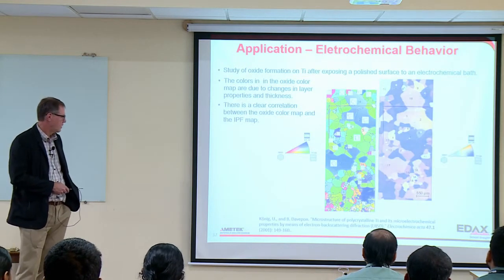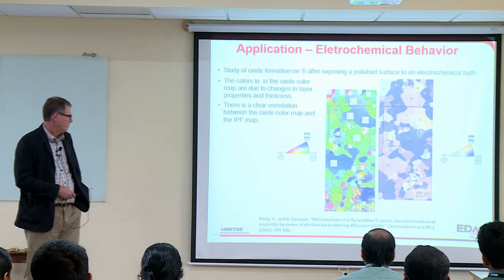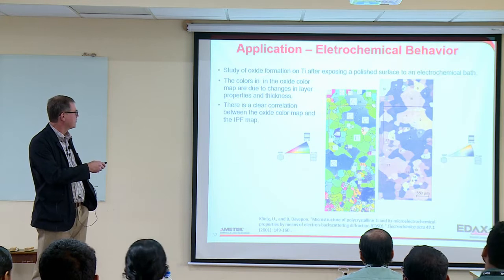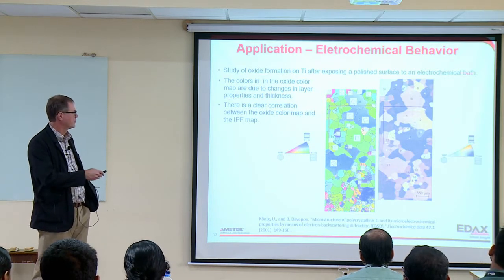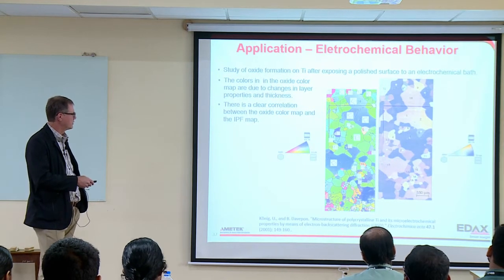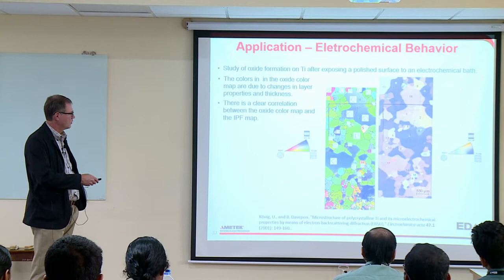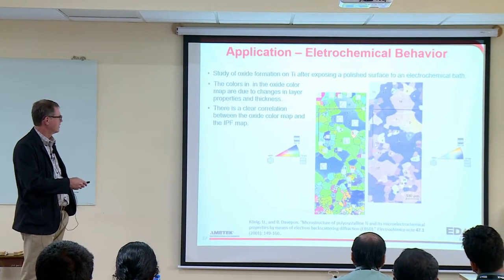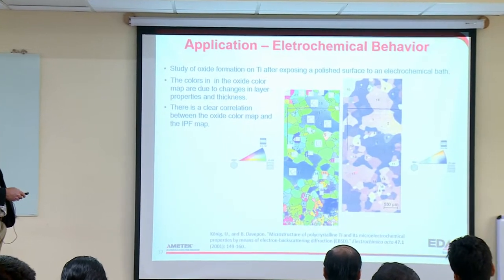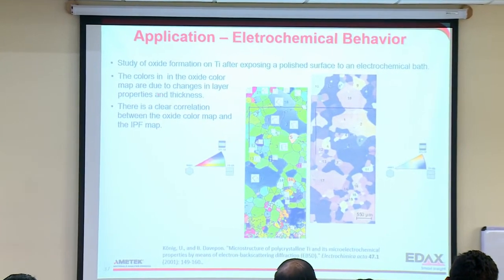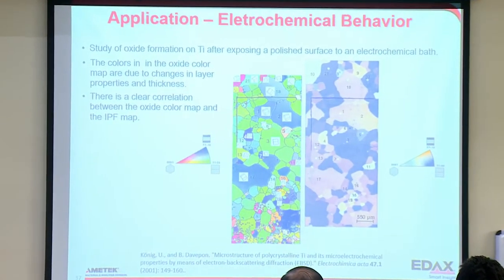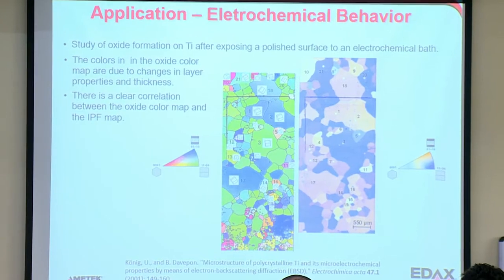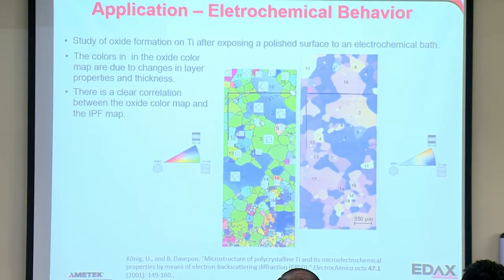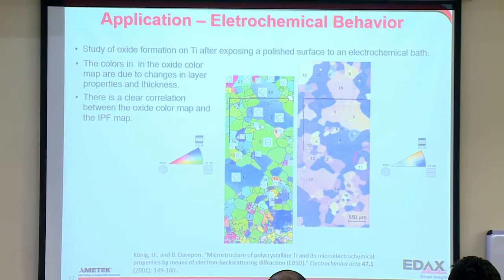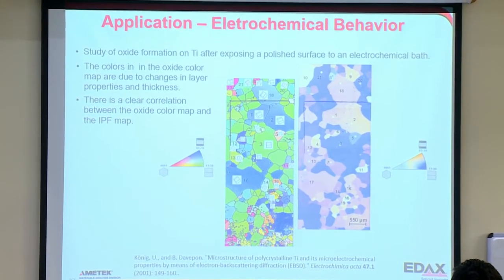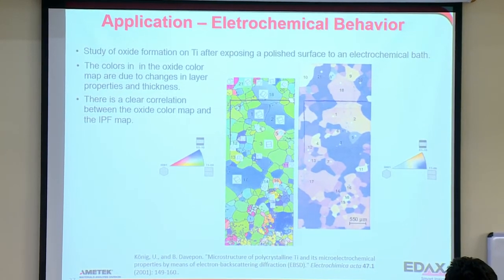Here's a nice application out of Germany from 2001. This is the study of oxide formation after exposing titanium to an electrochemical bath. What he did was correlate the crystallographic orientations with the activity, and they could measure this. Basically, the colors in this map are due to changes in layer properties and thickness, and they tell us something about the electrochemical activity. They used these little lines here as fiducials, and then took the EBSD data and put it in the map, and they were able to see a clear correlation between the orientations and the activity.